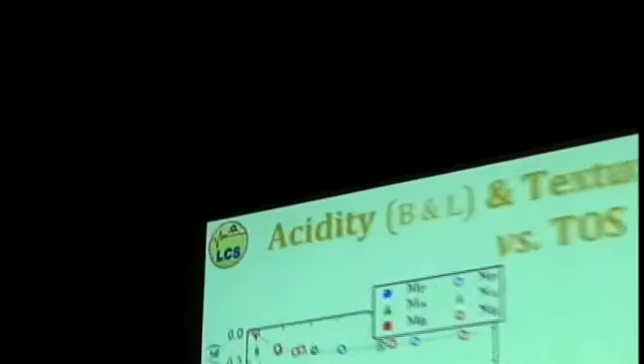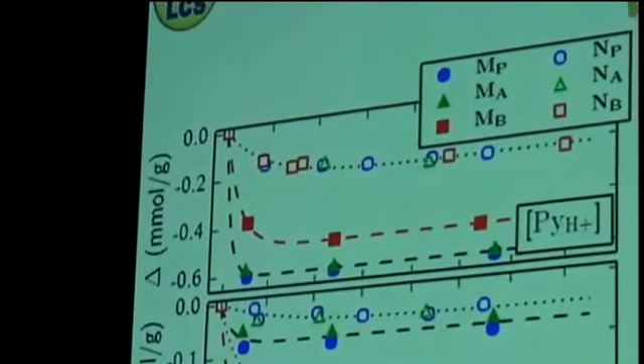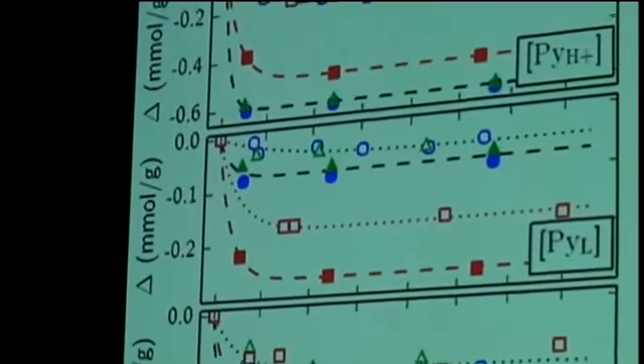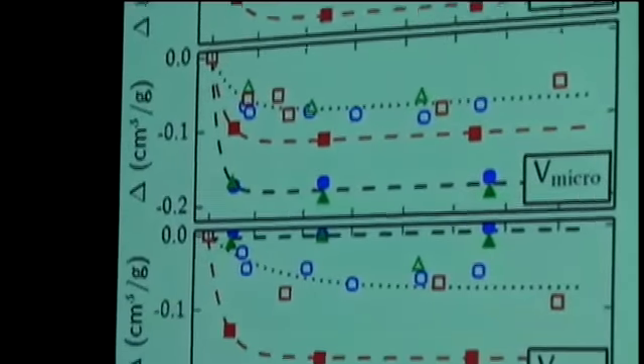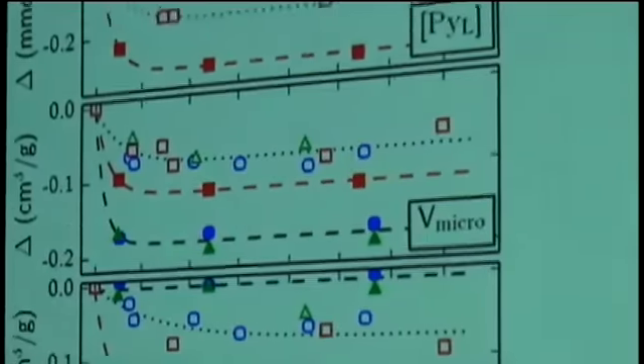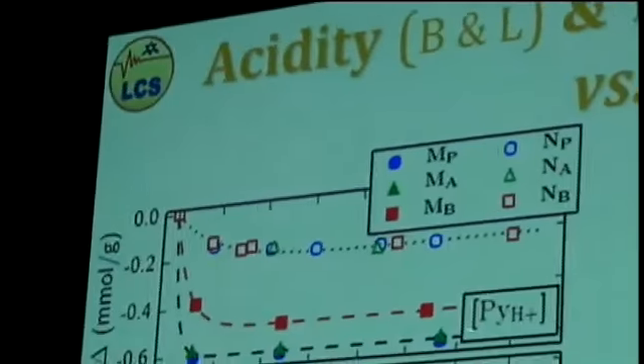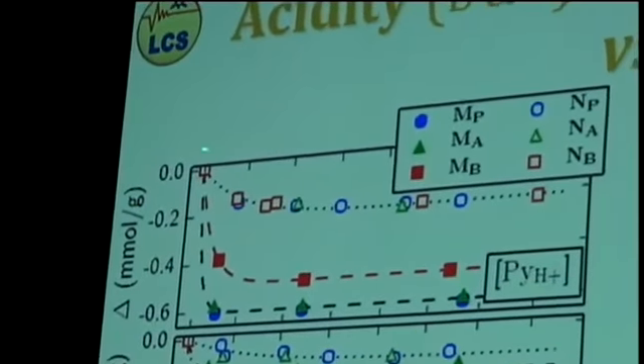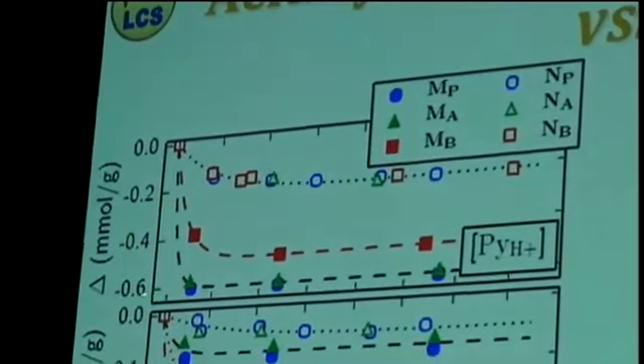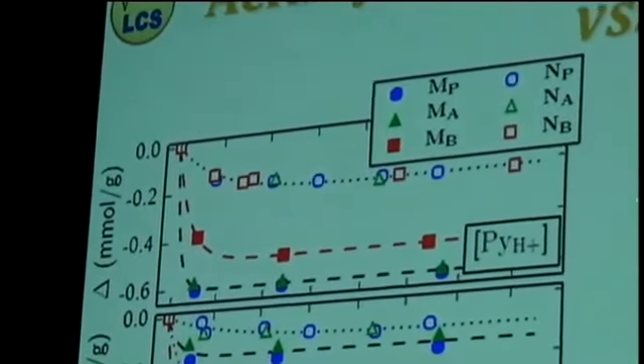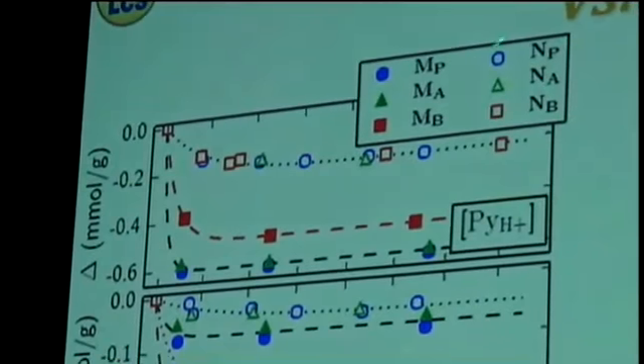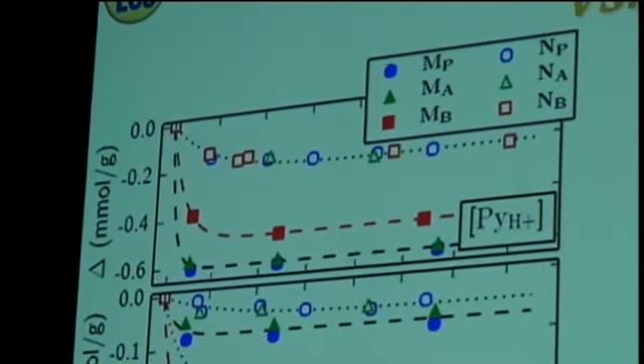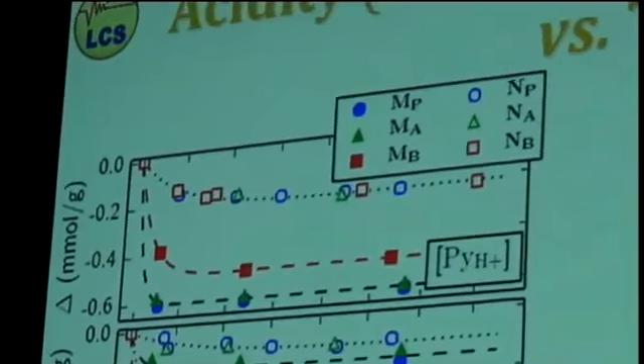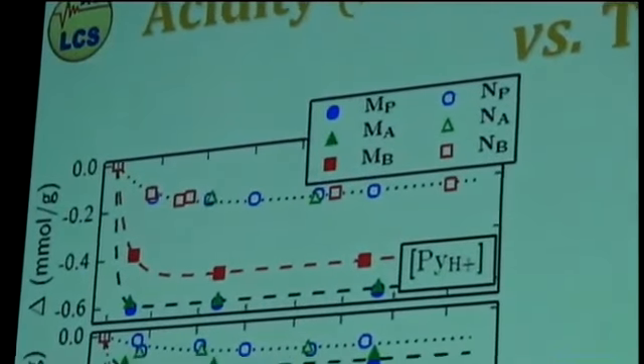So now let's have a look at another aspect: the acid sites, the number of acid sites present after a certain time on stream, and also the pore volume, micro and mesopore volume. I will concentrate only on the number of Brønsted sites. This is the number of Brønsted sites that disappear as a function of time. And keep in mind that the nano-sized zeolites have a higher silicon to aluminum ratio, so they have a lower number of aluminium.